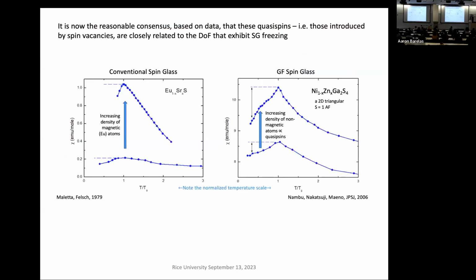So now let's look quantitatively at the difference between conventional spin glasses, such as europium strontium sulfide and nickel gallium sulfide. If you plot chi versus a reduced temperature, T over Tg, Tg being the glass temperature, you can see that as you put in more europiums, the signal goes up. Not surprising, right? You put in more of what you're interested in. Same thing with nickel gallium sulfide. No, actually, different thing. As you increase the density of non-magnetic ions, so the quasi-spin that I talked about, the signal goes up. So it's the same sense, only you're not talking about atomic spins, you're talking about composite spins.